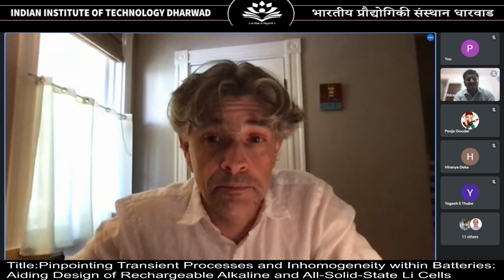So I do know that they use solid, brittle, high Young's modulus materials, and the lithium dendrites will grow along the grain boundaries inside of the solid material and still short it. So even if you have very strong materials, the dendrites will still short. Then the battery heats up. I think it's not as big of a safety problem, but it still is very bad for the battery. So it doesn't necessarily explode, but it still kills your battery. This is a very important problem to look at. So hopefully that's a good answer for that, although I wouldn't say I'm an expert on that particular thing.